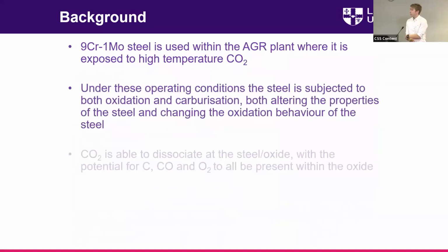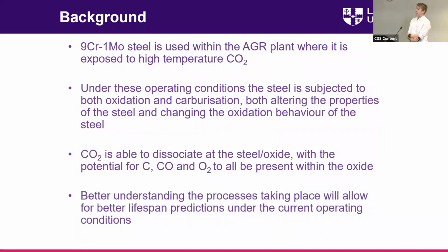So it's used in the AGR plants where it's exposed to high temperature CO2, and under these conditions it's exposed to both oxidation and carburisation. And these carburisation and oxidation change the properties of the steel with exposure time. The CO2 is able to dissociate at the steel and oxide, so carbon dioxide, carbon monoxide, carbon and oxygen can all be present, interacting with the material.